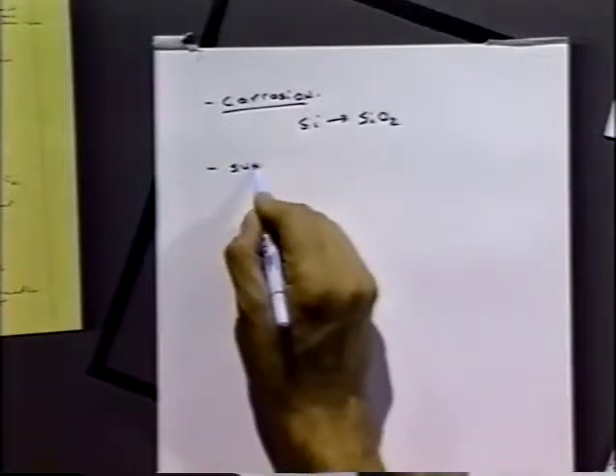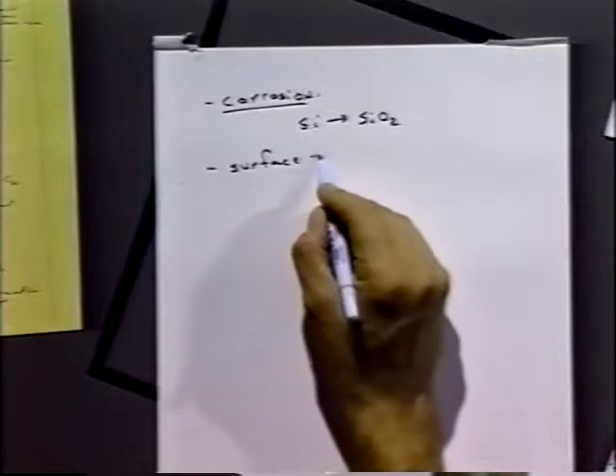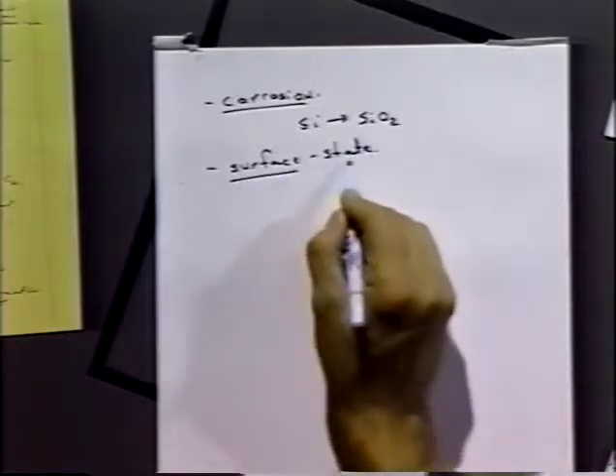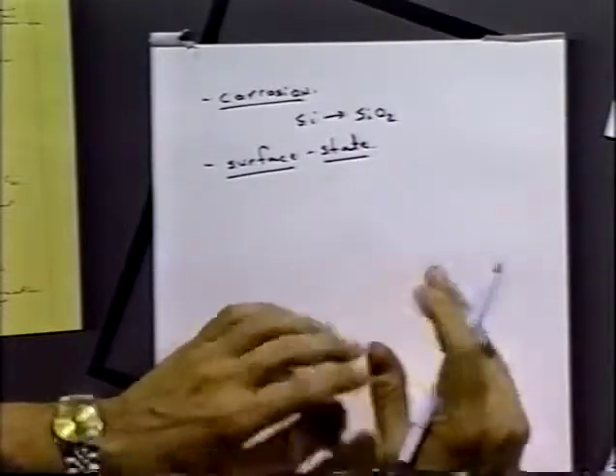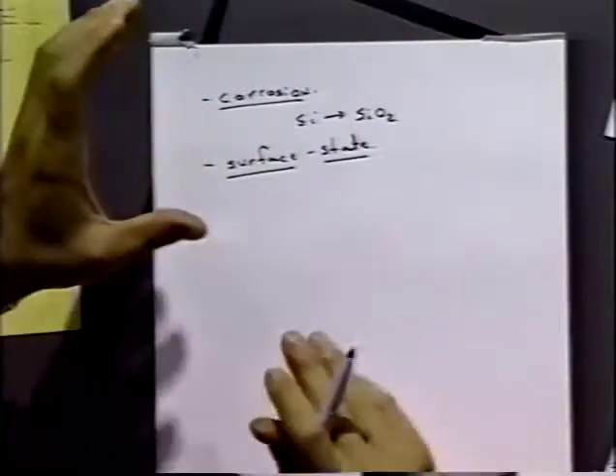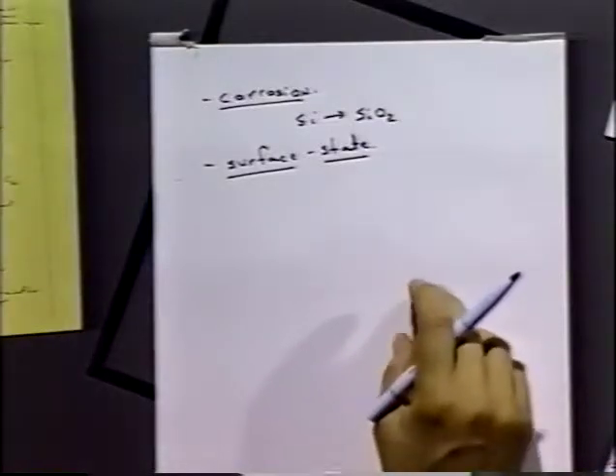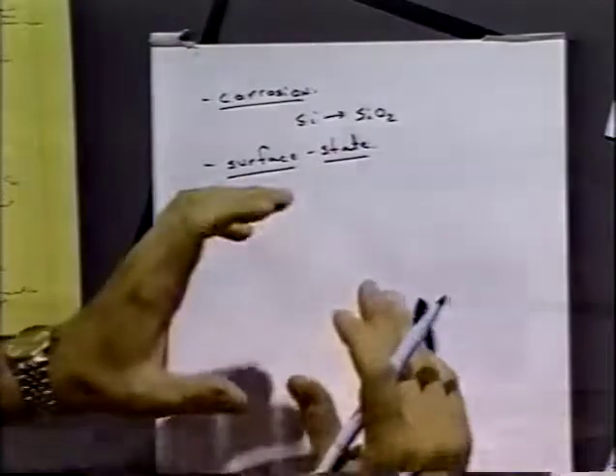Also, the surface itself is not the same as the bulk. I forget who said that, but somebody said once the surface was invented by the devil. And that's where everything happens, and things are different on the surface than in the bulk. So all the stuff we talked about in the bulk has to be modified somewhat for the fact that different bonds are present. Instead of the bulk silicon bonds, you've got dangling bonds where the silicon is exposed. So a lot of times they'll be terminated with hydrogen, as one way to do that. They'll expose the surface to hydrogen as a plasma or something to make it hydrogen terminated, or in an acid solution. And so that will cause lots of different things.